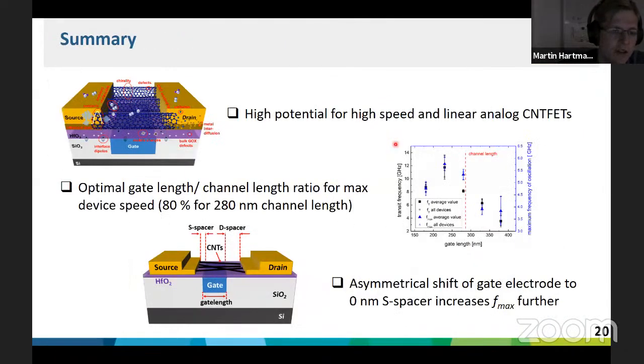So you need to have the proper device equipment at first, of course, because we do a buried gate approach and a planarized gate. That means that the CNTs are not bent anymore. If you would deposit the gate electrode on top of your silicon oxide and then just lay the CNTs on top of that, then you would bend your CNTs, which might introduce some issues into the final device. So you really need to embed them properly to have them leveled up with the silicon oxide, for example, in this case. So this is one issue.